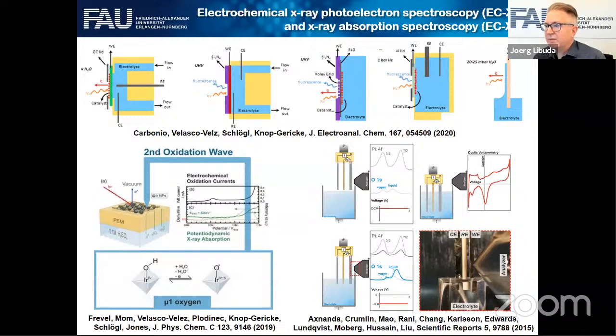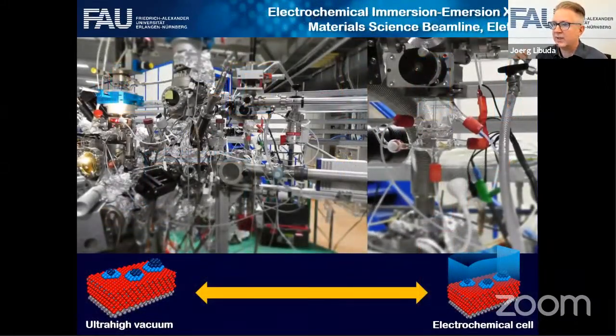But also there are things to keep in mind. I showed you before, it's a problem if you have these very thin electrolyte films, if they only have thicknesses in the order of a micrometer, with the infrared spectroscopy. It's difficult to control the pH. Here in this technology, you need films that are as thin as 10 to 20 nanometers. So if you run chemical reactions in there, you really have to be extremely careful what you do. You have to work hard to know what your electrochemical conditions are in this experiment. But still it's a beautiful experiment.